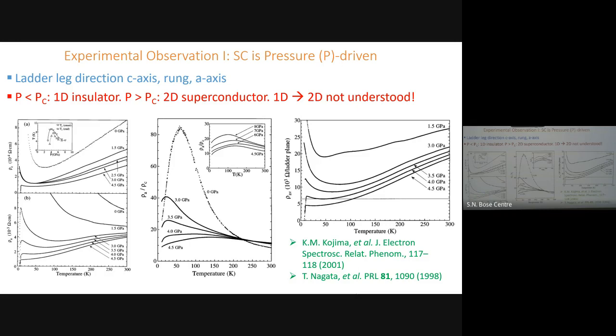And you apply pressure, it does do this. You take that resistance in the A direction over C direction, it actually at ambient pressure increases enormously. So the resistance in the A direction is increasing enormously over C by a factor of 80. You put pressure, it cuts down. So the superconductivity is under pressure. You take the geometric mean, it's standard practice in anisotropic materials, rho C times rho A. Take the square root of that and you plot a resistance. This line that you see is h over 4e squared. This is the resistivity here, to convert it. h over 4e squared is the universal two-dimensional resistance. The system is two-dimensional just before it undergoes superconductivity.